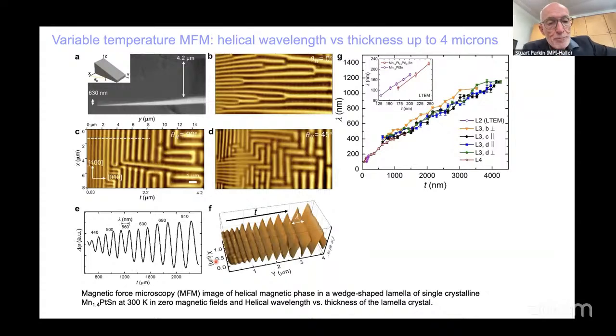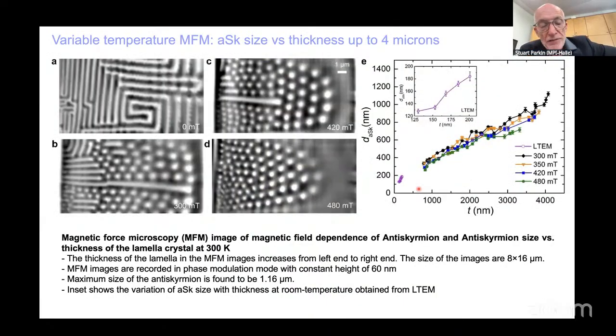slab, this lamella. And what we discovered was that the period of this helical magnetic phase increases uniformly with the thickness T of the lamella in which we image this one-dimensional helical object in this manganese platinum tin structure. So it turns out if we change the magnetic field, we can switch this helical structure shown in A to a series of these magnetic dots. These actually are antiskyrmions as imaged in the magnetic force microscopy.